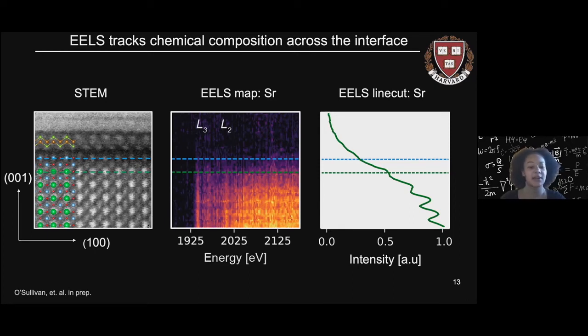So by performing this analysis for all of the elements, we're able to see exactly where each element resides in our sample. The strontium element in particular is very useful as we're able to do a fit that measures the instrumental resolution due to the finite size of the electron beam we fire through. Because we don't expect any strontium atoms above this dotted green line, we know that all of the signal above this line must be instrumental resolution. And so we're able to conduct this exponential fit, which we're able to then use when analyzing the EELS signals from our other elements, as I'll present in the next few slides.